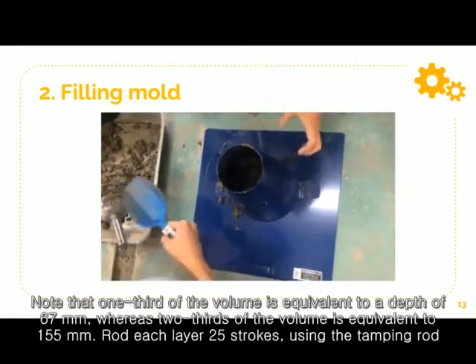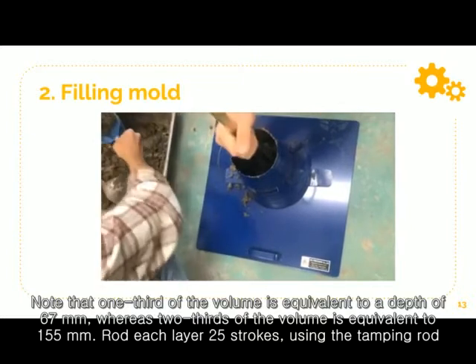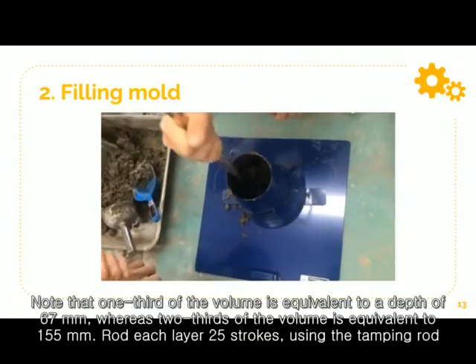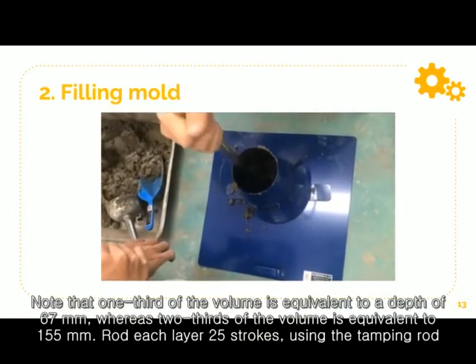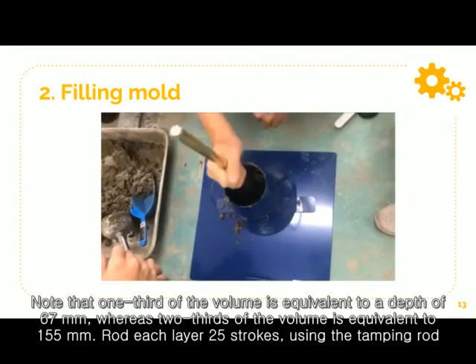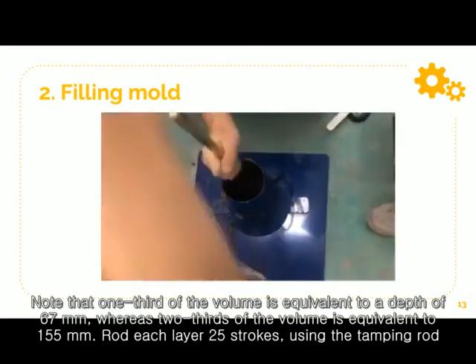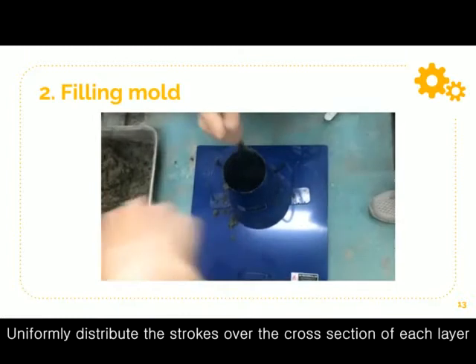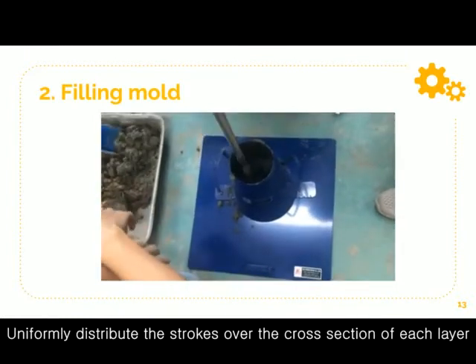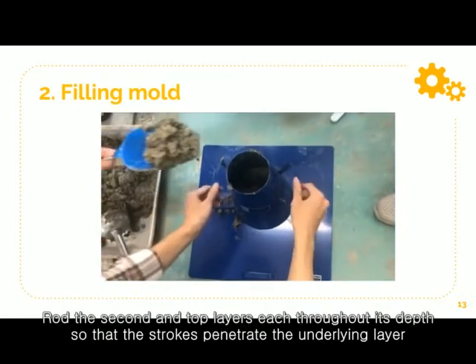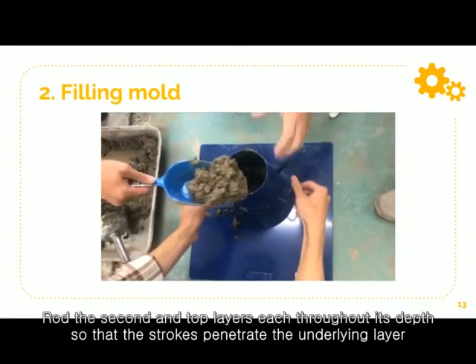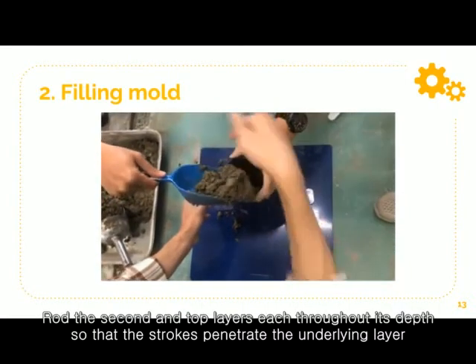Note that 1/3 of the volume is equivalent to a depth of 67 mm, whereas 2/3 of the volume is equivalent to 155 mm. Rod throughout each layer 25 strokes using the tamping rod. Uniformly distribute the strokes over the cross section of each layer. Rod the second and top layers each throughout its depth, so that the strokes penetrate the underlying layer.